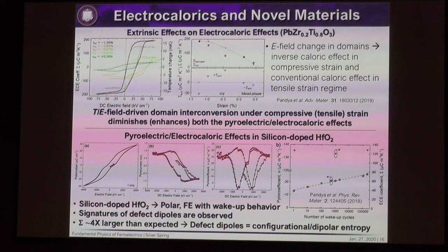But if you measure the electrocaloric coefficient, it is consistently high across all of the measurement cycles that we do, suggesting that there might be different contributions to what's going on. It is also 4 times larger than I would expect based on the pyro coefficient in these systems. This suggests that there might be something like defect dipoles, which could be responsible for this pinching that you see here, giving additional configurational or dipolar entropy that could be leading to larger effects in these systems. So this is something that needs to be studied more, but points to some interesting physics happening